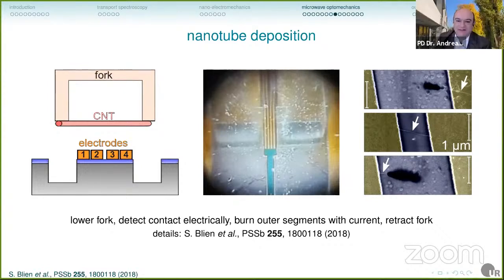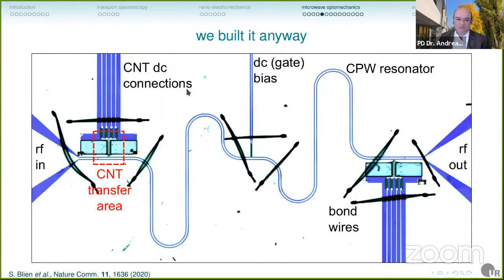We don't really have enough statistics yet to say that. The problem with the old fabrication is a very technical one, and it cost us a couple of years. Our first approach to this experiment was to basically make the chip and then grow the nanotube in situ. It turns out this is theoretically possible, and in practice has a yield of 0, because the high temperature growth process for the carbon nanotubes eventually destroys every superconducting resonator. So you can use the in situ growth and these ultra clean tubes for simple experiments, but it's impossible to do it with a complex chip.